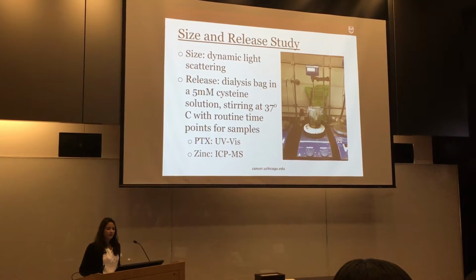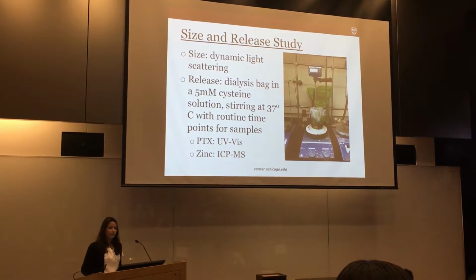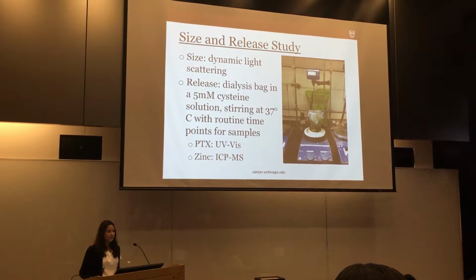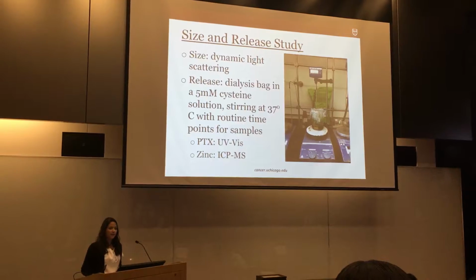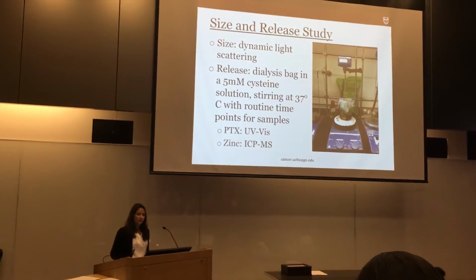The concentration and absorbance were plotted to form a linear trend line, and once the absorbance of the unknown samples at the same wavelength was measured, the equation of this trend line was used to find the concentration of the unknown samples. The concentration of zinc within each solution was measured using inductively coupled plasma mass spectrometry.